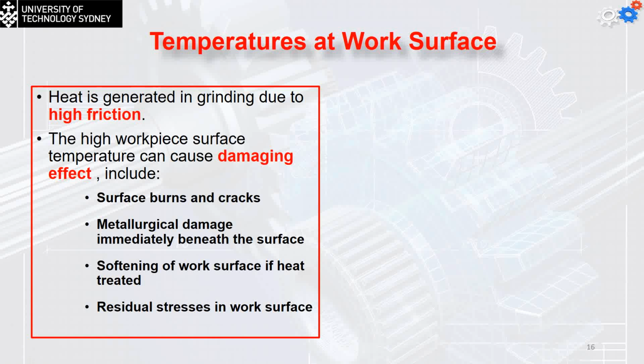We can have some metallurgical damage immediately beneath the surface because of the change in the crystalline structure of the material just below the surface, the whole surface. It's going to cause softening of the work surface if the part was heat treated, and residual stress in the work surface because of the higher pressure we have due to the temperature changes of the volume. Now, just remember these points. Okay, those are the effects of the temperature during the grinding process.